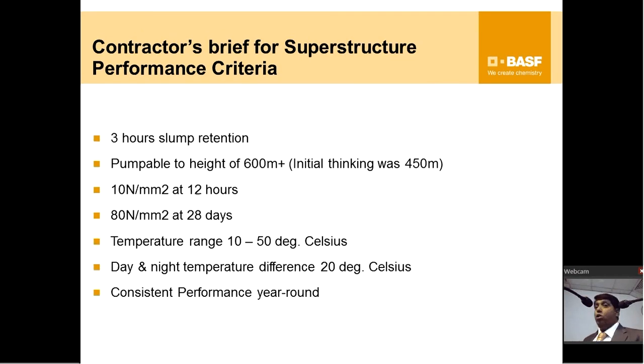For the superstructure, what they wanted is 3 hours of slump retention, which means you pump from the bottom and it reaches the top at 600 meters after 3 hours. So that's what this would require: pumpable to a height of more than 600 meters. Initially they were thinking about 450, but later on it went up to 600 meters. 10 newtons per millimeter square at 12 hours, very high. When this is the strength requirement, you cannot use a lot of retarder to give you that retention. You can use a retarder, but you cannot overdo it.